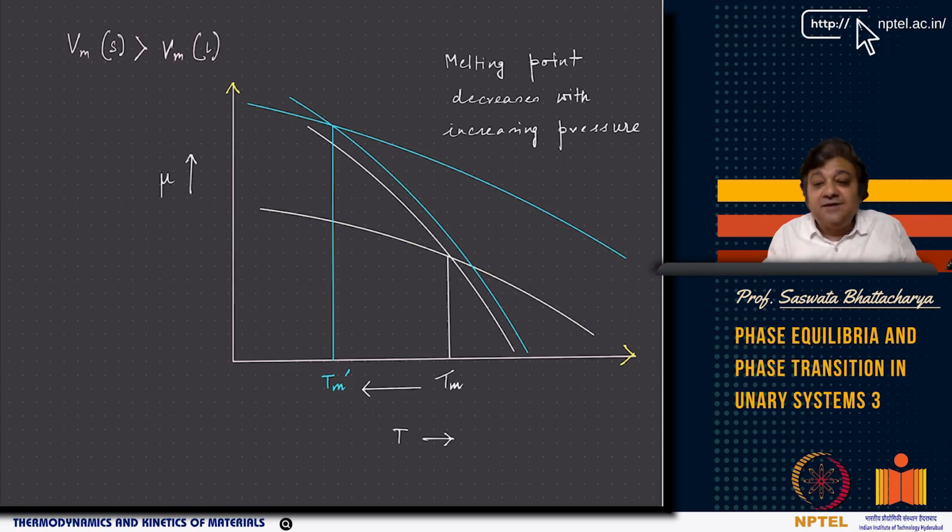So this is very interesting, very simple thing, but you just have to apply your logic and you can understand that. And remember, when I am talking about mu, the slope is what is changing. The del mu del P at fixed T, that means at a fixed temperature, the derivative of the chemical potential as a function of pressure is the molar volume. So if you have a mu versus P curve at each T, then the slope basically gives you Vm.